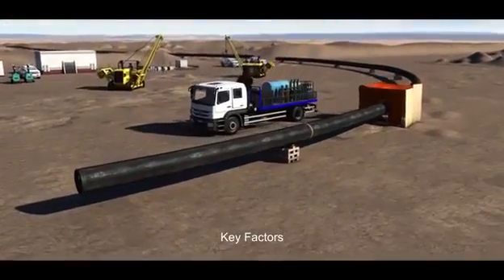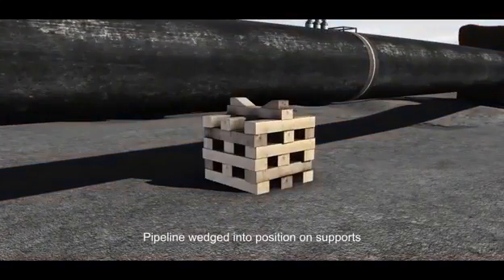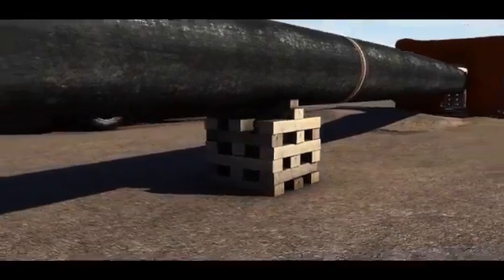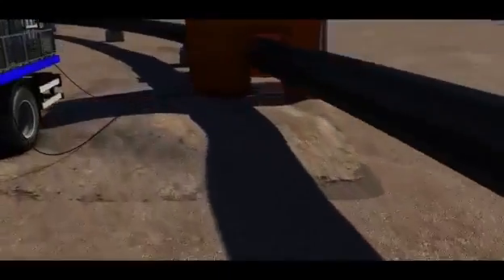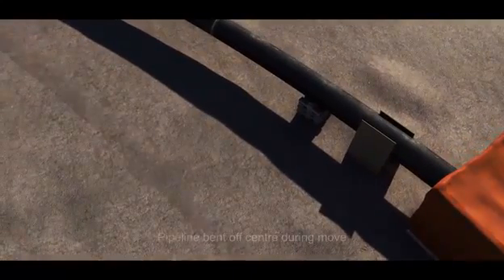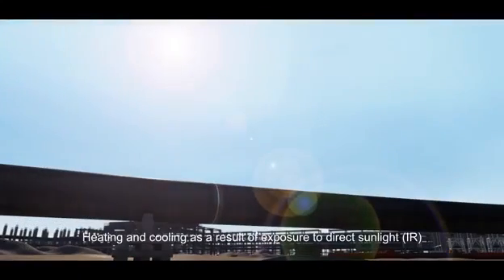So what went wrong? The pipe was wedged into position on the stack, which would store energy from pipe flex and thermal effects. The support stacks were unable to accommodate the pipe should it move. The pipe was bent off centre when being repositioned, which created flexing energy. The pipe was differentially heated by infrared energy from sunlight.